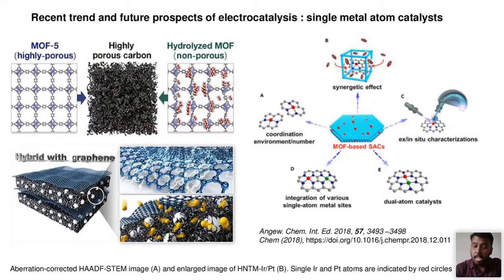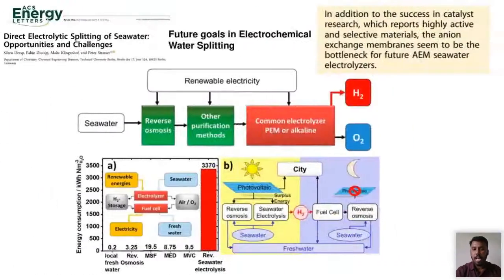People are trying to develop single metal atom catalysts. Instead of having a nanoparticle of 50 nanometers or 100 nanometers, people are trying to develop metal organic frameworks that can be carbonized, and can generate dual atom catalysts or single metal atom catalysts. A single metal atom catalyst means it will be about 1 nanometer in diameter. So 1 nanometer means very, very small, and you have a large number of sites in a particular area. In that way, you can increase the number of active sites.